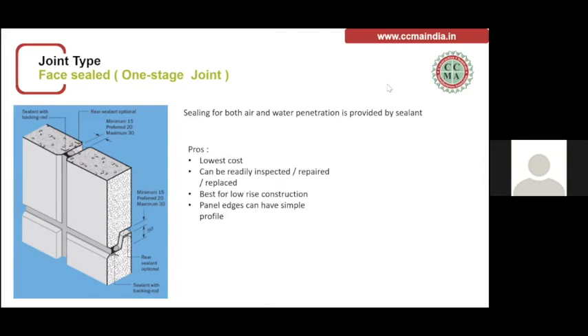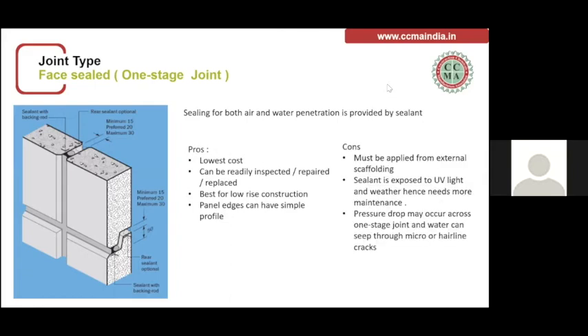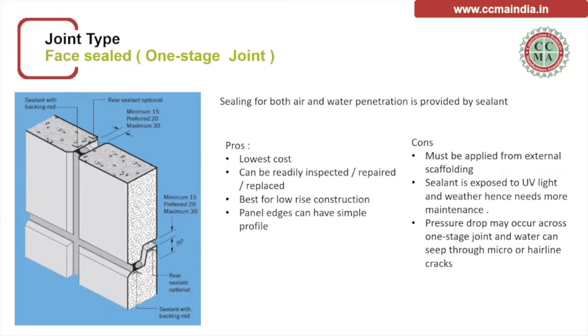What are the advantages of this method? First is the lowest cost, and it is widely used for this reason. It can be readily inspected, repaired and replaced. It is best for low-rise construction. Panel edges can have a simple profile. Disadvantages: it has to be applied with external scaffolding. Sealant is exposed to UV light, so there will be faster deterioration. And another important disadvantage is that a pressure drop may occur across the one-stage joint when there is wind-driven rain during a storm, and water can seep through these micro or hairline cracks.